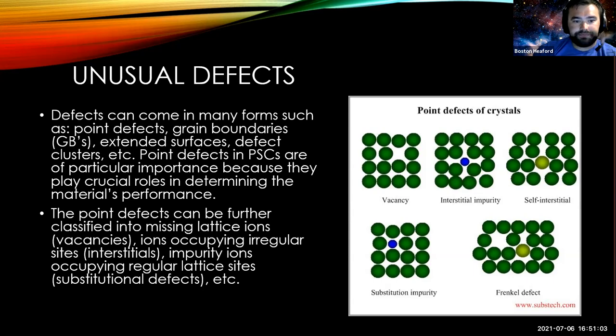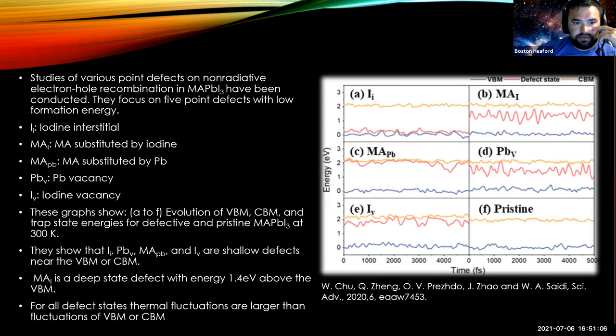But some of the influences of point defects were studied. And here's a list on the left of the different kinds of point defects. There's the iodine interstitial, methyl ammonium substituted by iodide, methyl ammonium substituted by lead, a lead vacancy and an iodine vacancy. And these graphs show the evolution of the valence band, conduction band and trap state energies for these defects, as well as the pristine system.